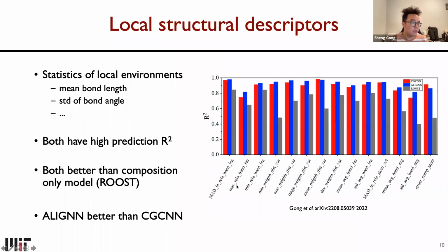Okay, so the first kind of descriptors we want to examine is local structure descriptors, which are essentially statistics of local environments like the mean bond length and the standard deviation of bond angle distribution in this crystal structure. And we can see that both CGCNN and ALIGNN we just introduced before have high prediction R-squared score. Both CGCNN and ALIGNN, which take geometry into account, have better prediction than the composition-only model, which we use as a baseline. So we found that the input of geometric information improves the prediction. And also ALIGNN is better than CGCNN at capturing these statistics of local environments, which is reasonable because ALIGNN takes more geometric details into account.